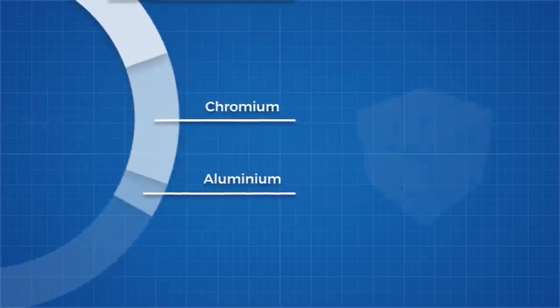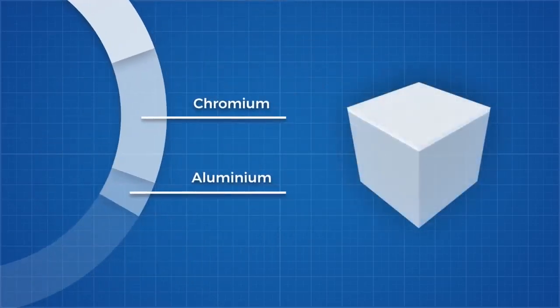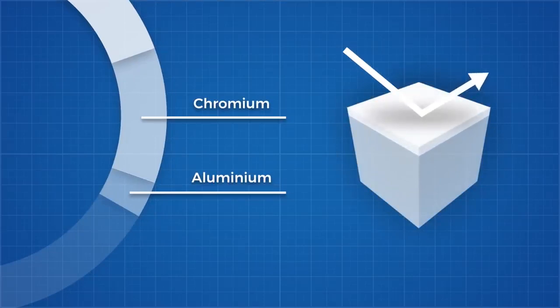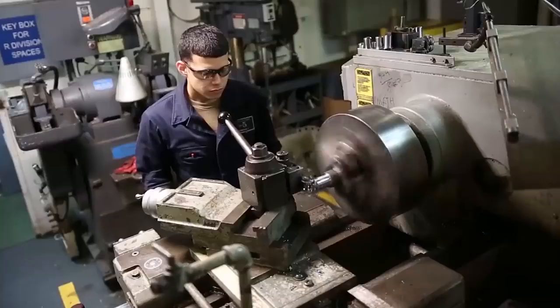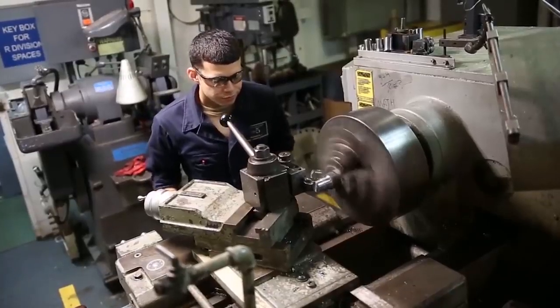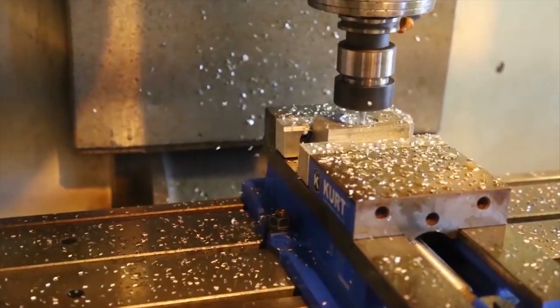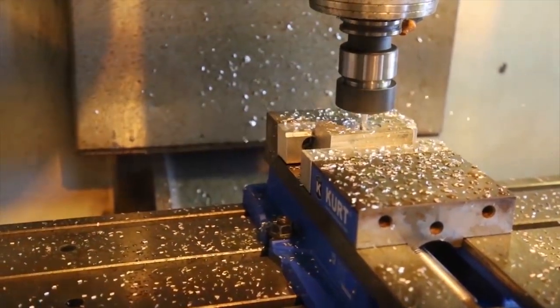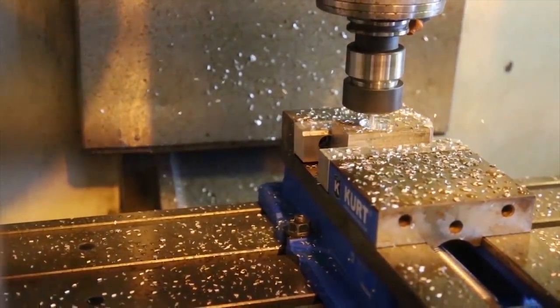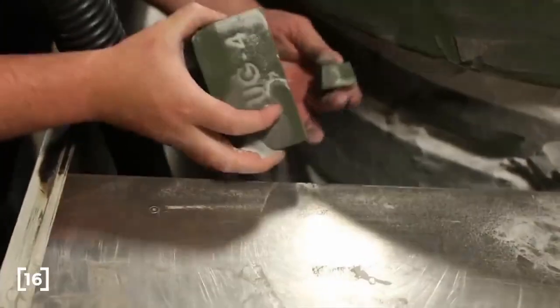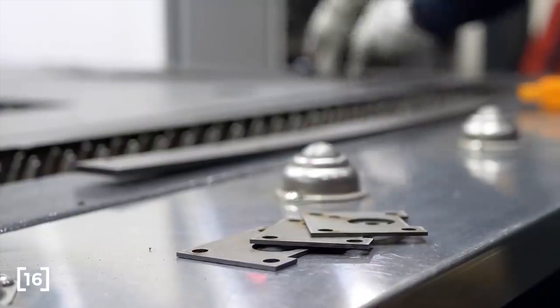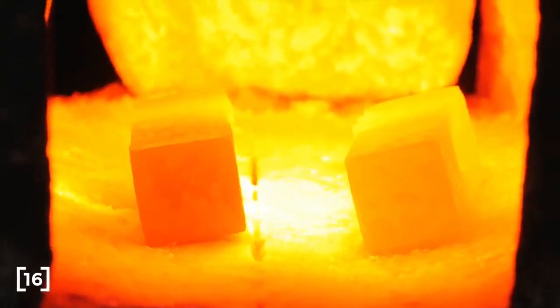Both chromium and aluminium form thermally stable oxide layers on the outer skin of the metal, which prevents oxygen from diffusing further into the metal and causing it to become even more brittle, which raises the max operating temperature of the metal, while the vanadium acts as a stabilizer for a crystal structure referred to as the beta phase, which leads to a material with higher tensile strength and better formability, with an ability to heat treat to a higher strength.